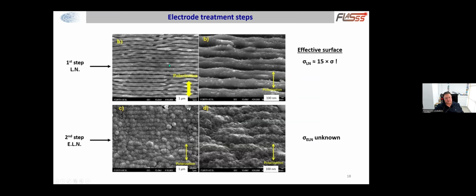On the upper side of this figure, you can see the typical periodic pattern, the so-called ripples. And on the upper right side, when we zoom in, we can measure the period of these ripple patterns. Also, you can notice there are several nanoparticles distributed all over the surface of these samples. And by analyzing the intensity profile, we calculate the effective surface to be increased by as much as 15 times. And for the second class of samples, the electrodeposited samples, this is how the SEM micrographs look.